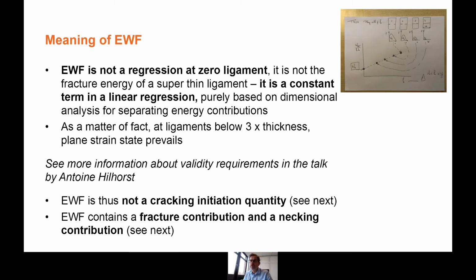And again, more information will be given by Antoine about the limits on the size of the ligament and the selection of the ligament. The two points I would like to bring to your attention. First, the essential work of fracture is not a cracking initiation quantity, like already explained by David, but I want to go one step further to reveal probably the main origin of this, the fact that the essential work of fracture should not be considered as a cracking initiation quantity.